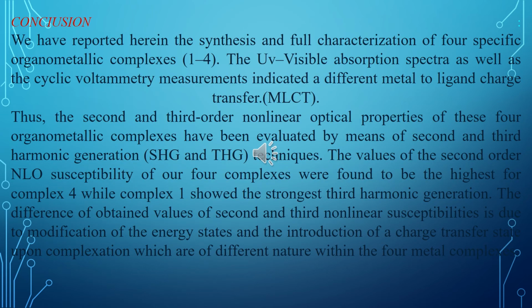In conclusion, we have reported herein the synthesis and full characterization of 4 specific organometallic complexes. The UV visible absorption spectra as well as the cyclic voltammetry measurement indicated a different metal-to-ligand charge transfer MLCT. Thus, the second and third order nonlinear optical properties of these 4 organometallic complexes have been evaluated by means of second and third harmonic generation techniques.